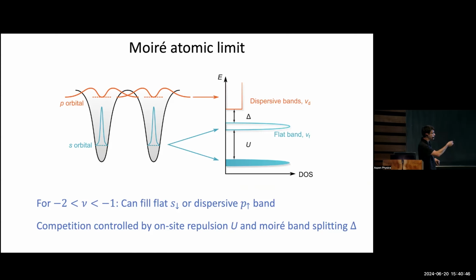Then these p orbitals give rise to more dispersive bands. So these s orbitals are very flat because there's very little overlap between them. The p orbitals, on the other hand, give rise to dispersive bands. And you have a choice. If you're filling first hole per Moiré unit cell, it's clear you want to put them in this energy band. But as you fill the next hole between 1 and 2, you can choose one band or the other. So as I've drawn it here, say you want to occupy this upper Hubbard band. Remember, this upper Hubbard band now has some opposite spin relative to the lower Hubbard band. These dispersive bands can have same spin. And so the relative alignment of these two possible bands to occupy is now dictated, for example, by the applied magnetic field that you have in your system.